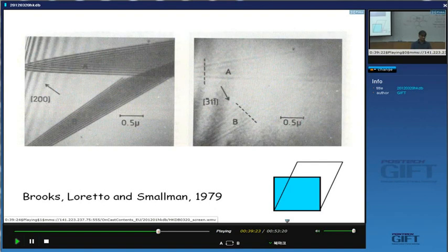And in this paper, they also studied a sequence of alloys where the volume change should be different. Right? So if you change the concentration of cobalt, then the volume change on the gamma to epsilon transformation changes, and the contrast here changes. If the volume change is almost 0, the contrast disappears. As the volume change becomes bigger, the contrast becomes darker.